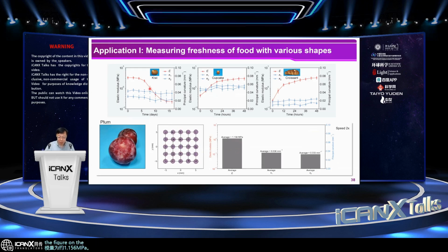The figure on the top illustrates the long-term monitoring of the elastic modulus and principal curvatures of a kiwi, cupcake and croissant, which is very difficult to achieve using previously reported schemes. And here, for the kiwi, you can find a certain time period in which the modulus reduces rapidly. And excluding this time period, the kiwi modulus changes very slightly and very slowly.